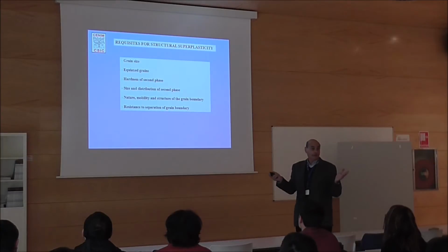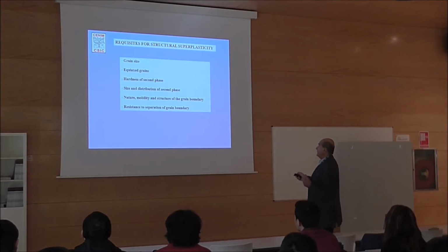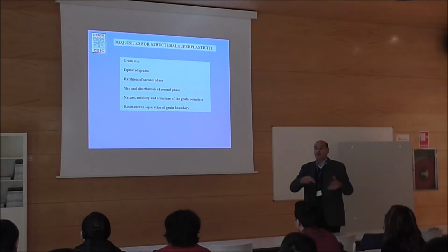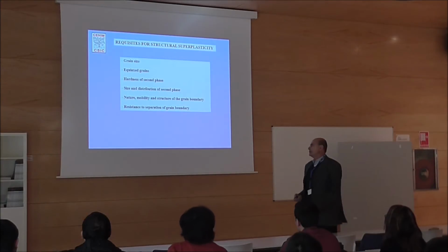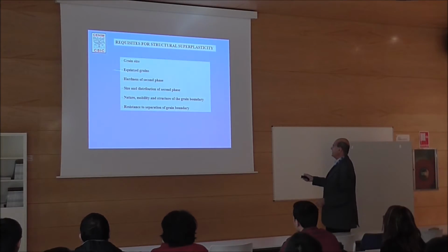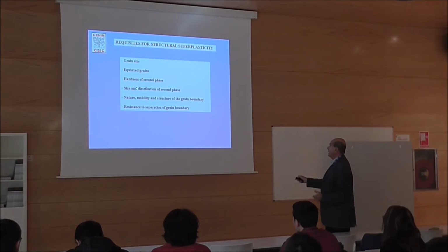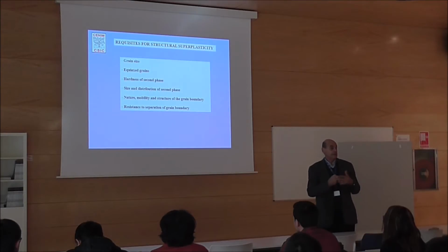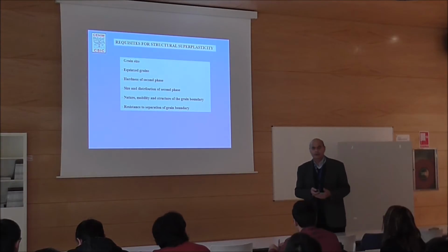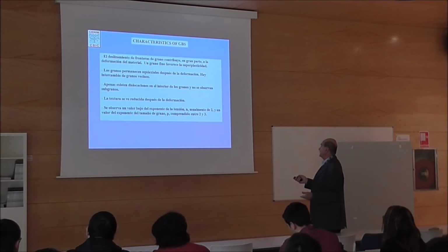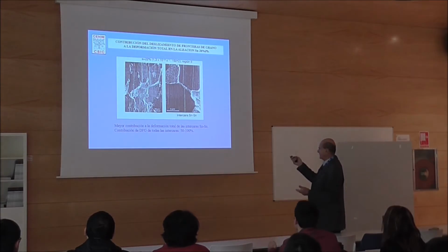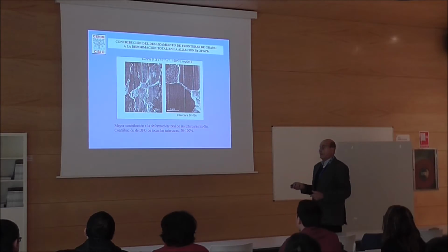And that brings a whole new field of deformation. The grain size is very important. After 2000% deformation, you have equiaxed grains, but imagine if you had slip, you would have strings, not grains. The hardness of the second phase is important, and then the nature, mobility, and structure of the grain boundary are important. And you have texture. The texture disappears in a material. And there are hundreds of papers on this. I'm not going to have time to show that every single point has been correlated to experimental data.